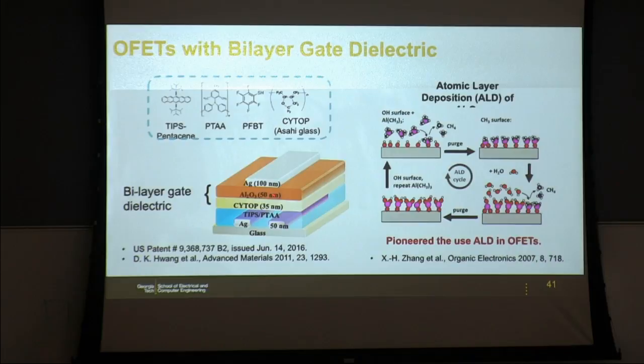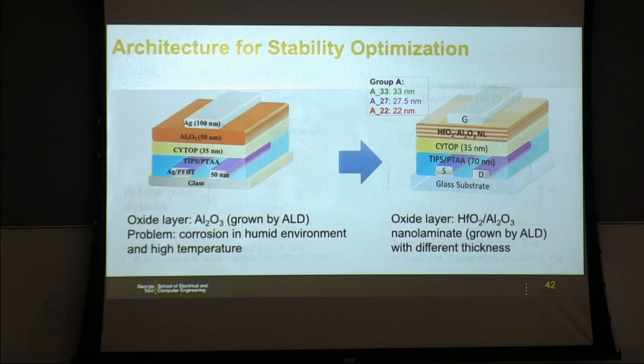But then we were lucky because we basically stumbled across a discovery, totally unexpected as usual, that there was a synergy between the Cytop and the aluminum oxide in terms of lifetime and degradation. Before I tell you what it is, I just want to tell you that we've made a small improvement recently because we found aluminum oxide by itself undergoes corrosion in a humid environment, and so that was a weakness.